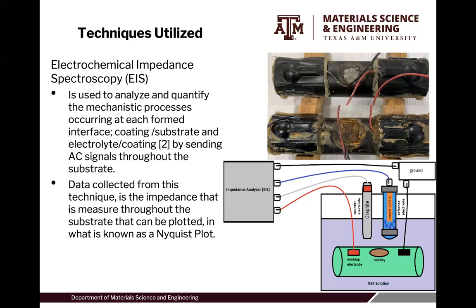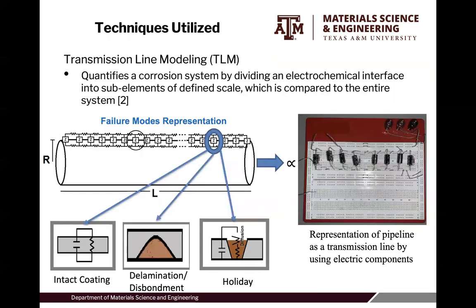Data collected from this technique is impedance measured through the substrate, which can be plotted in what is also known as a Nyquist plot. Another technique used is transmission line modeling, known as TLM. TLM quantifies a corrosion system by dividing an electrochemical interface into sub-elements at the fine scale, which is then compared to the entire system.